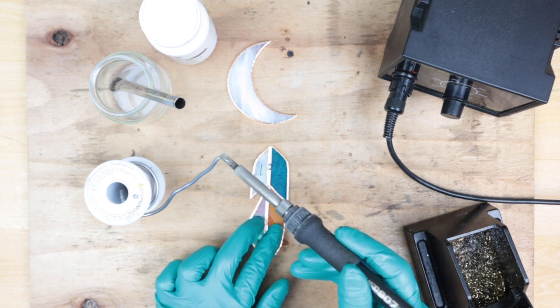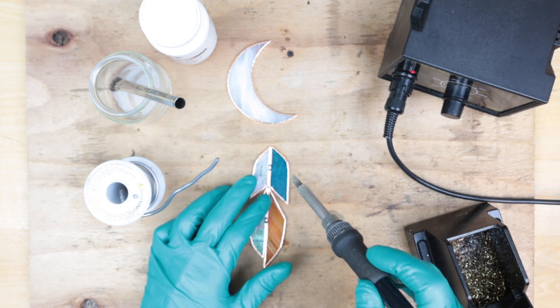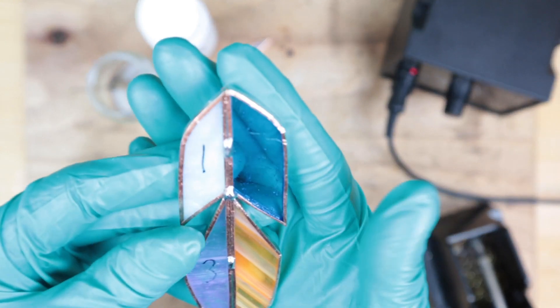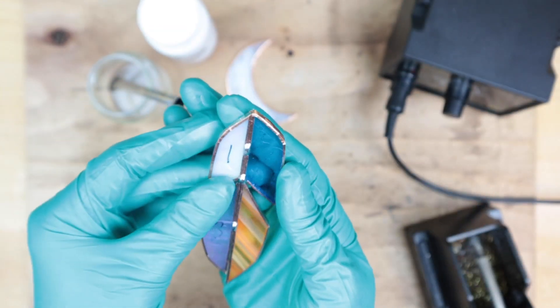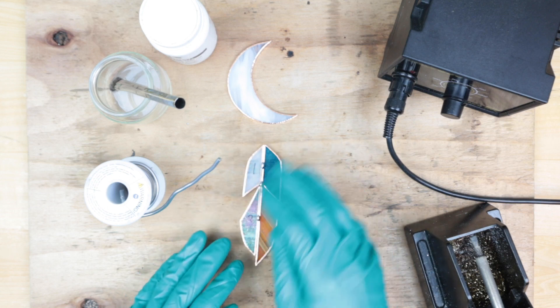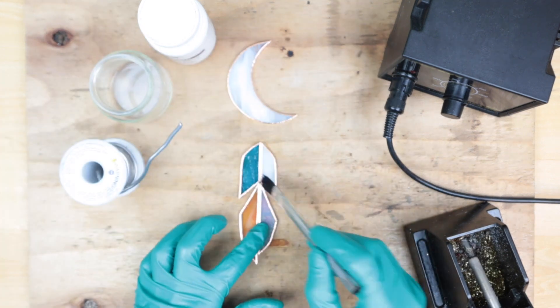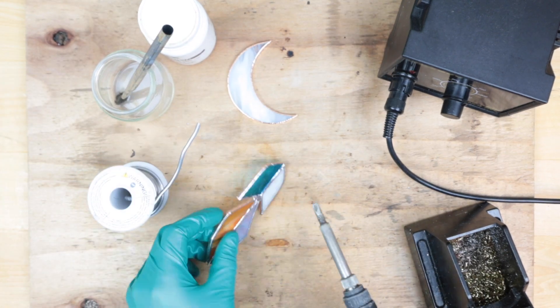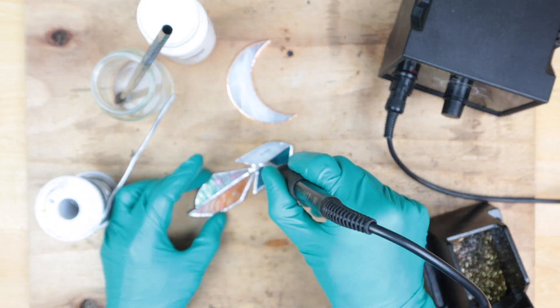I like the positioning of where everything is. Use two first, a little bit of solder, melt it down. You see that we've got the three spots that we just tacked on. It's only held together on this side right now so just be careful when you're handling it. Now let's add solder to the rest of it. Just add flux and then add solder to get nice bead lines throughout. Make sure you don't stay in one place too long or else you may crack the glass or delaminate the copper foil. Just keep your temperatures down at first and figure out a nice melting point.